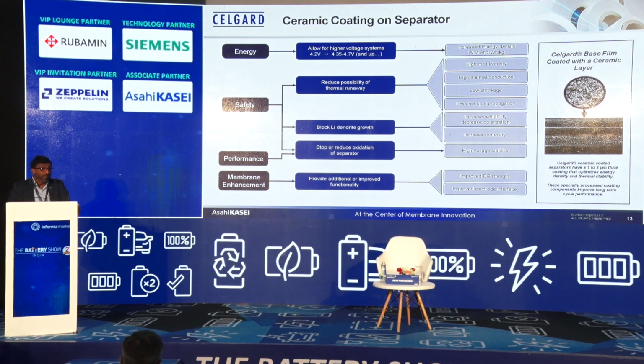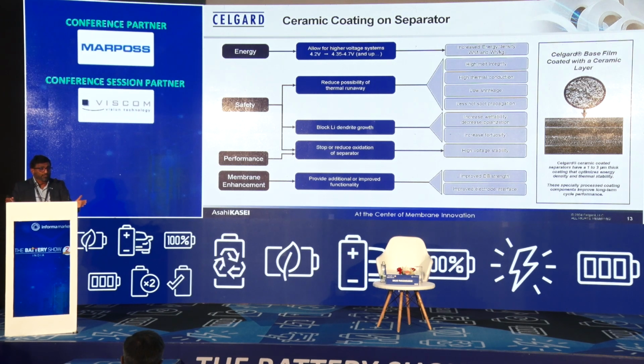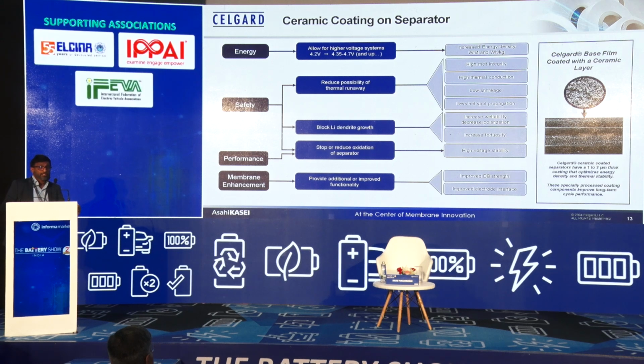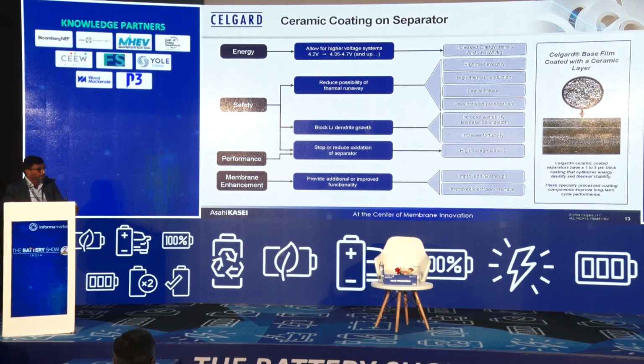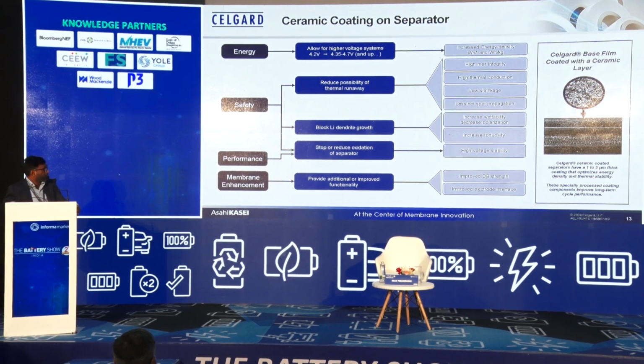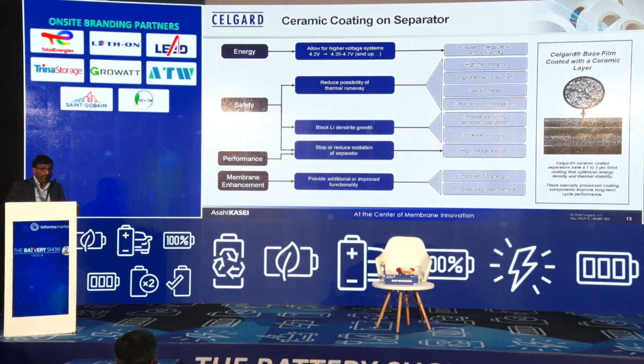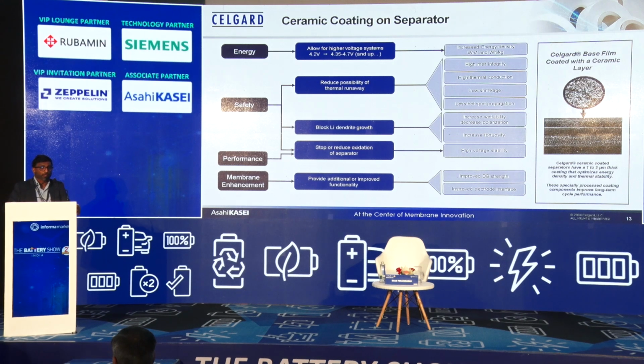So ceramic can dissipate the temperature to a wider area, so that there won't be any hot spot generating, so that the separator will not get damaged or shorting will not happen. And the third thing is it can avoid dendrite growth, because the dendrite has to pass through ceramic. It is going to take more time, so it can delay the dendrite growth inside the cells. And ceramic is also a very good oxidation resistant, so it will give a higher life. For higher cycling, we prefer to go for ceramic coated separators. That being said, we can also do two-side or single-side ceramic coating as per customer requirement.